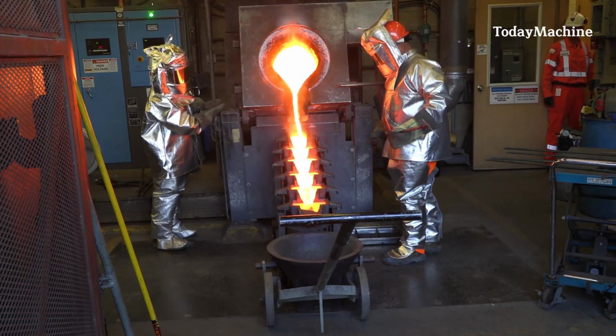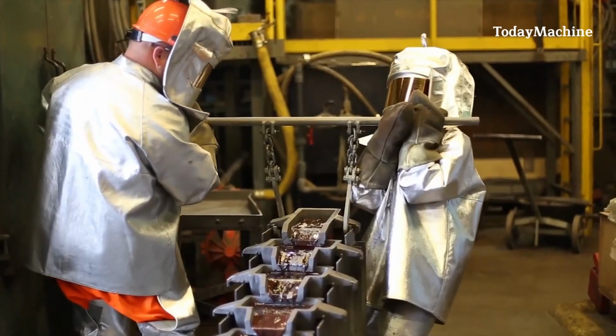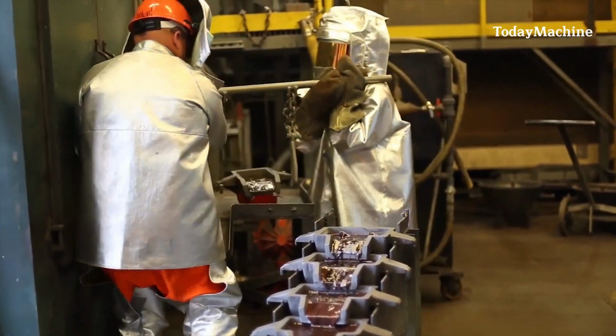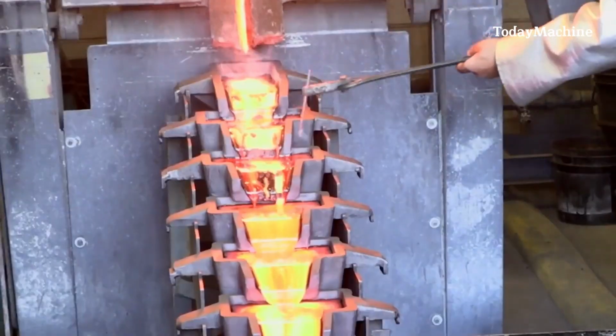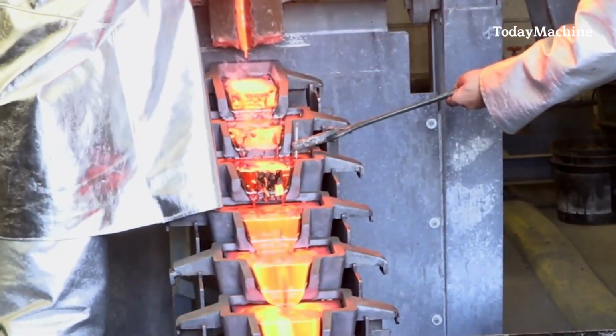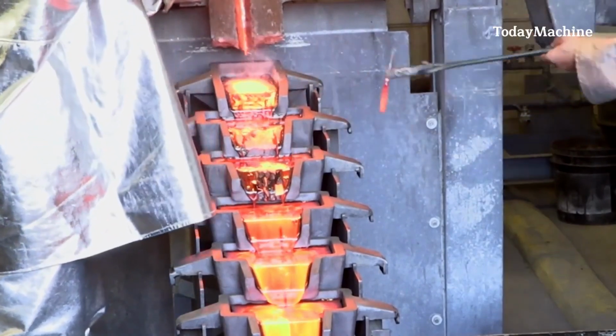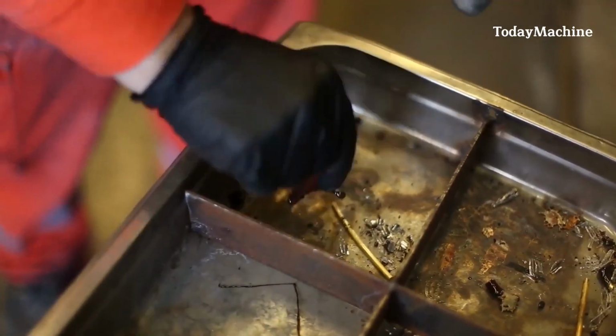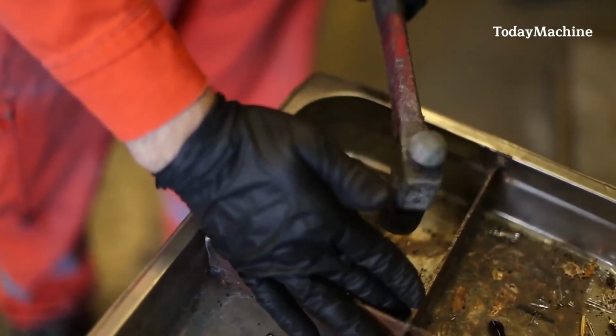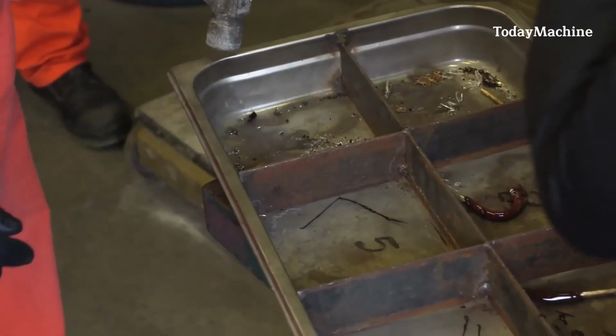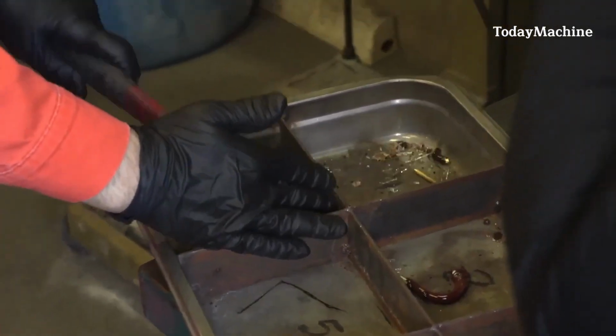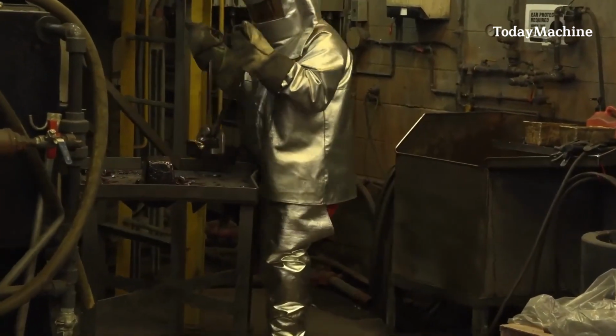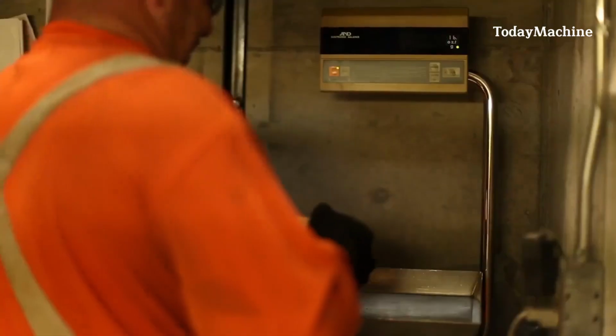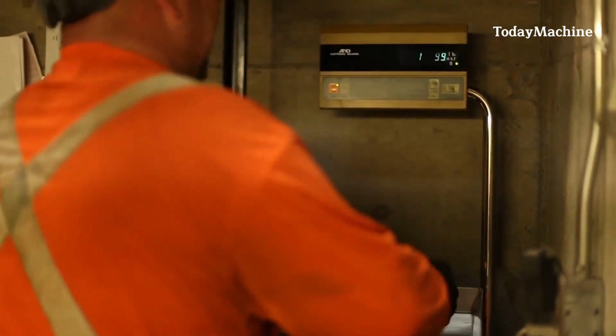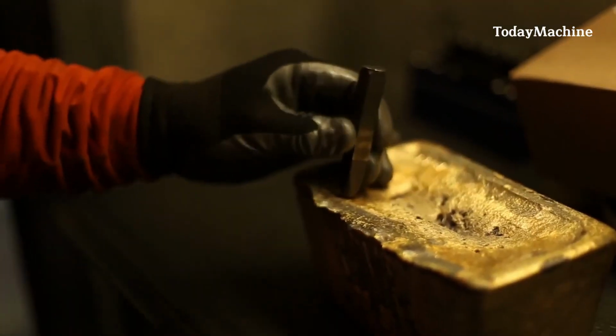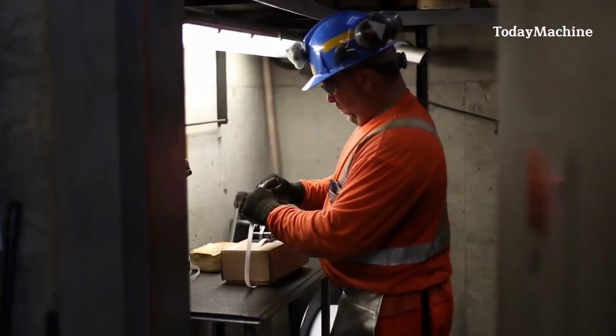After the molten gold is poured into molds to form bars, a sample is extracted to determine the gold and silver content. This sample is carefully taken and analyzed to assess the purity of the gold. Typically, the gold content in the bars ranges from 80 to 90%, indicating a high concentration of pure gold. Additionally, the sample is also examined for its silver content, which usually falls between 6 to 12%. These precise measurements help ensure the quality and value of the gold bars before they are cooled, weighed, stamped, packaged, and sent to a refinery for further processing.